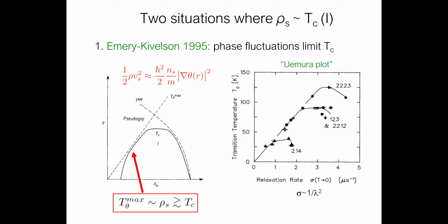There are a couple of mechanisms which are pretty well known for how this can happen. One of them is if you're in a regime where the phase fluctuations limit the critical temperature. This is Vic Emery and Steve Kivelson's idea from the 90s. So in the underdoped regime, this θ_max, the phase stiffness temperature, if you like, limits the T_c in this picture. And the mean field transition temperature, which is decreasing as you overdope, again presumably because the interactions are weakening, controls the critical temperature on the overdoped side.